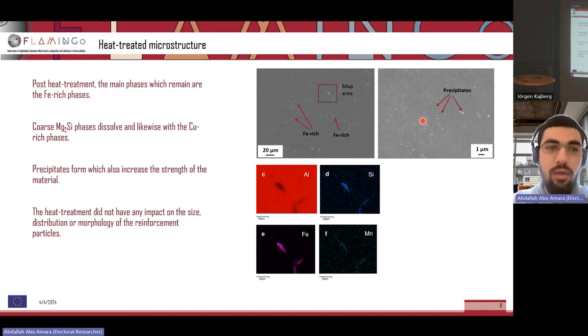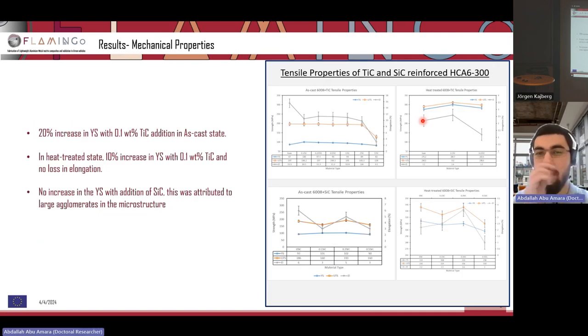And speaking of strengthening, I can quickly talk about some of the tensile properties that we were able to achieve with the additions of titanium carbide and silicon carbide reinforcements. In the top row, you can see the tensile properties of the castings containing titanium carbide. On the left-hand side, this is the as-cast material. And on the right-hand side, this is post-heat treatment, so once the material was heat treated and tested again. And in the bottom, you can see the same for silicon carbide. So this is as-cast and this is heat treated.